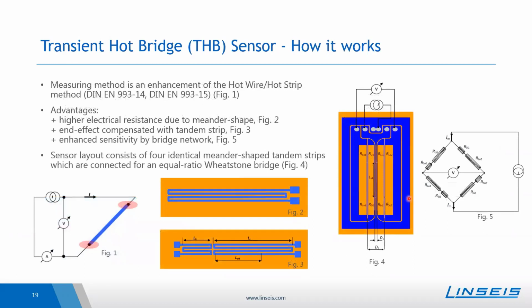The THB is an enhancement of the just shown hot strip or hot wire technique. So the start of the thermal conductivity determination was the hot wire, and due to some different layouts, we have here such a meander shape, and this is separated and connected to a Wheatstone bridge. Because of that, there are some advantages. So one has a higher electrical resistance, one compensates end effects, and one has an enhanced sensitivity because of this modified layout. The temperature increase, which one needs for the evaluation of the thermal conductivity, is directly connected to the bridge voltage, and because of that, one is then able to find out the thermal conductivity of the material.